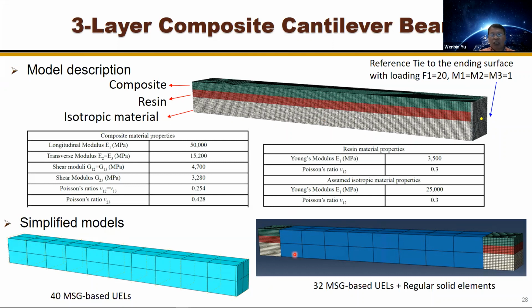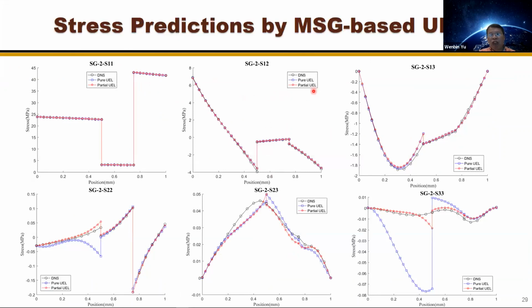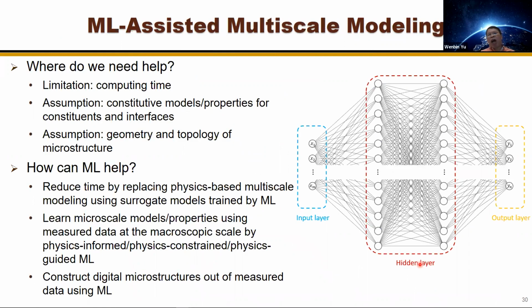But I take this section here close to the boundary, but it's already homogenized. We find that pure UEL does a good job for the in-plane stresses. Both approaches work okay. But for the transverse stresses, although they're small, they could be very important, for example, for delamination. And when we use the partial UEL, it's significantly improved. It's very close to the DNS, but the pure UEL has a pretty significant difference. So this method really works pretty well, and we are happy about that.